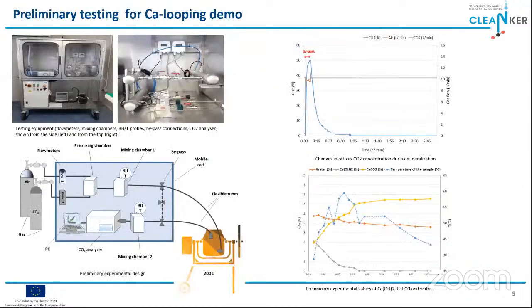And the preliminary tests that were done in Italy were put into practice. A CO2 gas stream was artificially prepared by mixing CO2 and air in different concentrations, allowing CO2 concentrations to vary. The 200 liter pilot was designed based on a commercially available concrete mixer integrated into the calcium looping demo system, and equipped with inlets and outlets, as well as CO2, temperature and moisture sensors to detect the reaction progress.